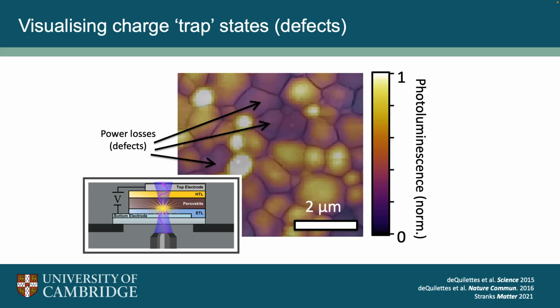These films typically are polycrystalline, so they're made up of these very small grains, mosaic grains. And what we see is some of these grains are really dark and poor, they don't emit much light. So remember, these are the ones that have lots of defects in them, and the other regions are really bright and emissive. And this is what we want. We ideally want a uniformly bright image here. And so there's some very interesting power losses here that we're trying to get rid of, and I'll talk about that as well.